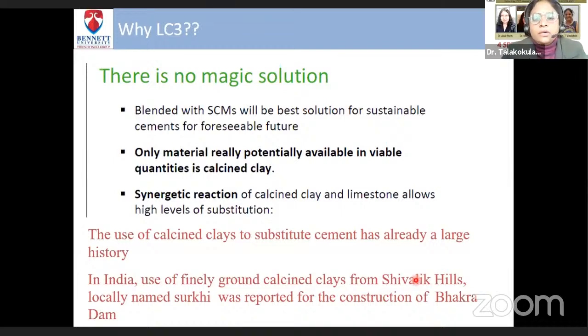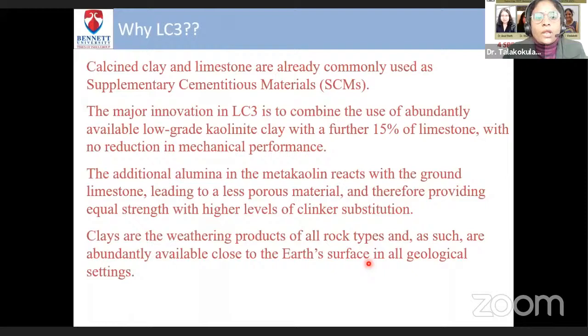But the proportions which were used for the replacements were not that high during those years. So the reason is this development in technology where we can use higher proportions of these substitutions to reduce the clinker content. So the major innovation in LC3 is to combine, as I told, abundantly available low-grade kaolinite clay with a further substitution of 15% of limestone, with no reduction in the mechanical performance. The additional alumina in the metakaolin reacts with the ground limestone, leading to a very less porous material. The skin of the concrete produced using LC3 is less porous, therefore providing equal strength with a higher level of clinker substitution.